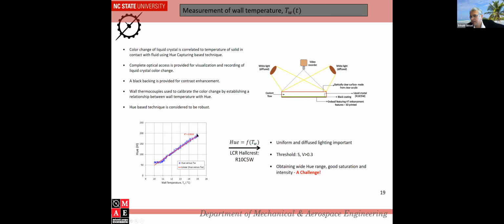Early on in the liquid crystal world, in 1990, somebody found out that hue is directly linearly related to the wall temperature. So we do a calibration in the experiment where we calculate our hue from the color, and we have a thermocouple which measures the temperature right at the same region. We plot the hue versus temperature and get a linear relationship, and then we take all the images and convert the hue at any instant of time to temperature. Then you get a temperature field at every instant, every frame in the experiment, and then we convert that to the heat transfer coefficient.